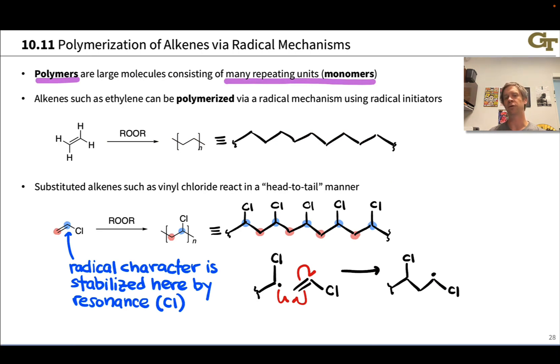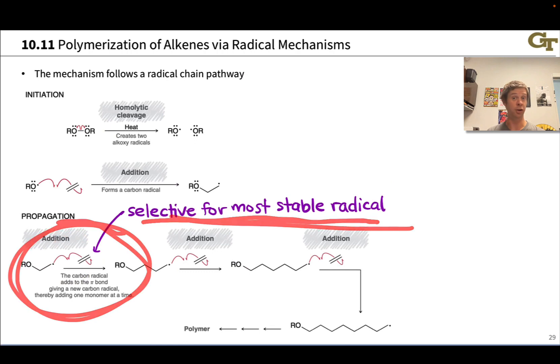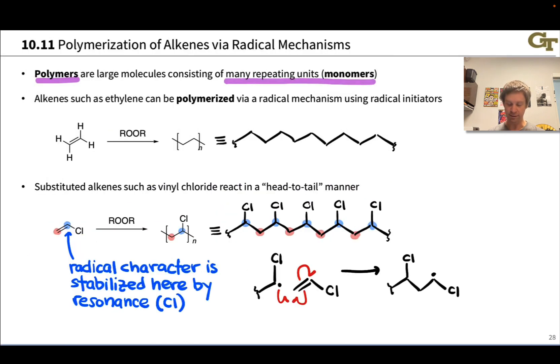This slide shows the radical polymerization mechanism for ethylene in full detail. It's a chain mechanism: we have initiation, where the peroxide homolytically cleaves and adds to the first molecule of monomer to create the first radical. That radical adds another molecule of ethylene, we get another radical, and so on. This radical addition step is selective for the most stable radical, which is why vinyl chloride polymerizes consistently in a head-to-tail way, ensuring the newly generated radical is on the blue carbon where it's stabilized by resonance with the adjacent chlorine. This is also a good exercise in fishhook arrow pushing — try drawing the alternative resonance form showing how chlorine shares radical character in this alpha-chlororadical.